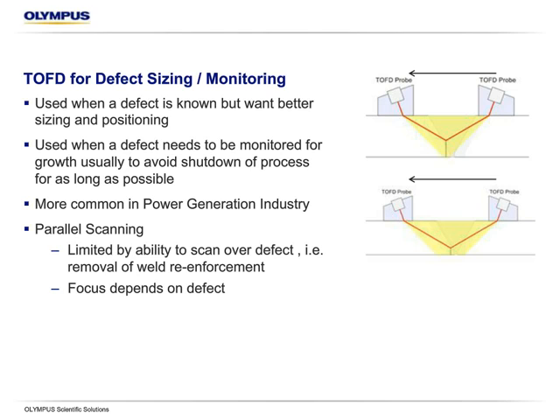So for defect sizing and monitoring, typically we do this only if we know a flaw exists. It's used a lot in nuclear, as well as some oil and gas and some other industries. Basically we have a flaw, but it's not at critical height or length yet. TOFD is very good for this, typically in the parallel fashion, where if we can remove that reinforcement or we don't have reinforcement, we'll get a first sizing, and then at a certain interval of time we'll keep going over and over that flaw and just see if that defect, typically cracks, is growing. It's pretty limited, but mainly in the power generation industry.